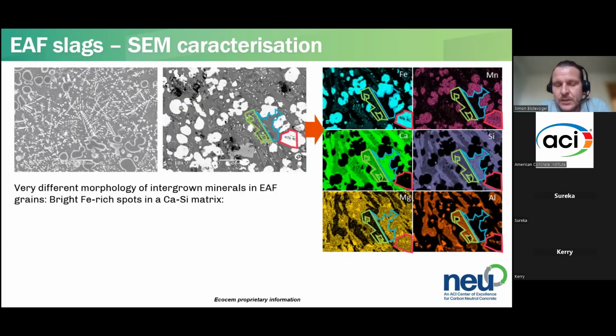If we look at current EAF slags here in these SEM micrographs, they are cooled down slowly, so we get a crystalline matrix and those funny white dots. The funny white dots are the iron oxides, which are not pure. I already said that it would be iron II, so it's a magnesio-wüstite kind of structure, or in slag language, RO phase, with some ratio between magnesium, iron, and manganese.